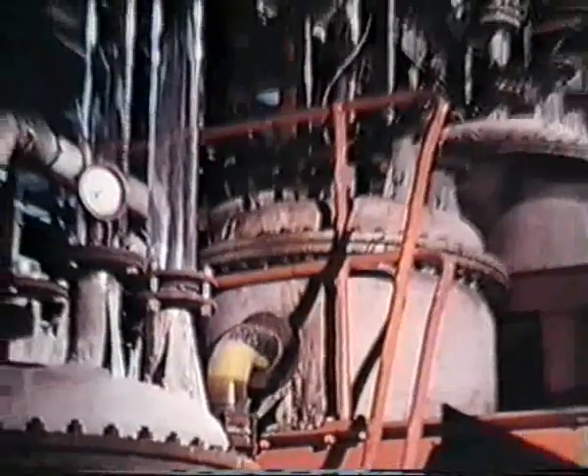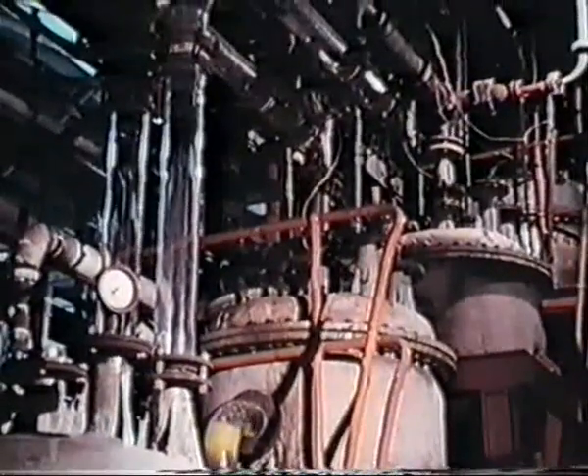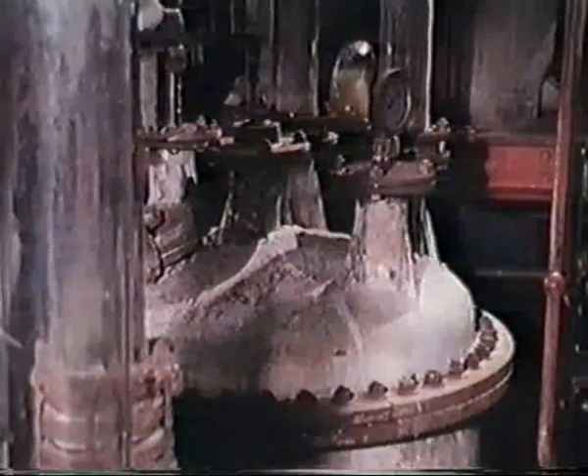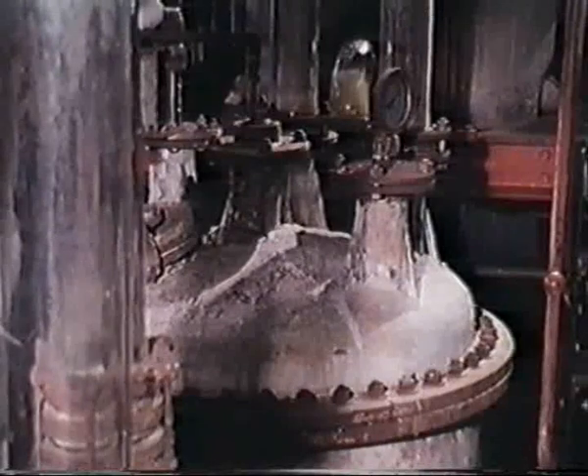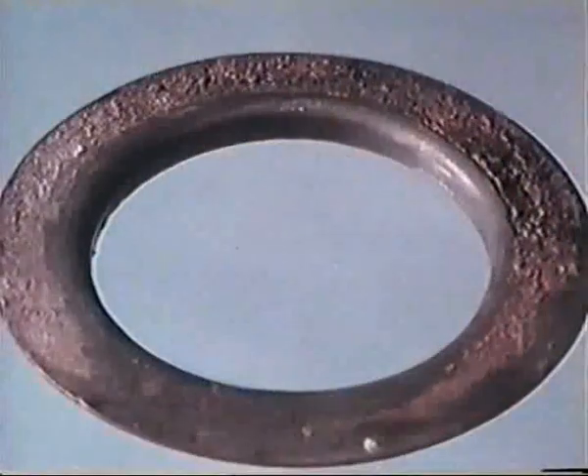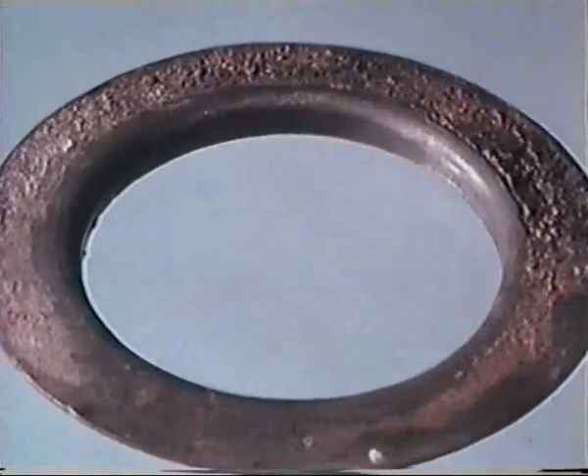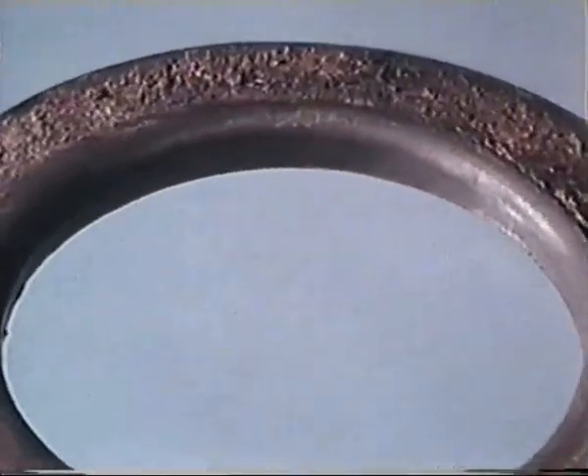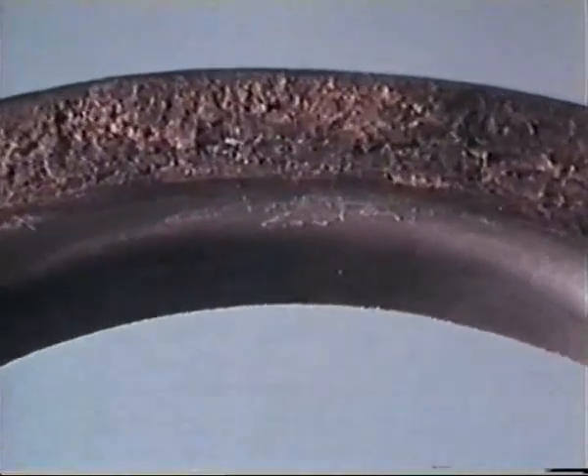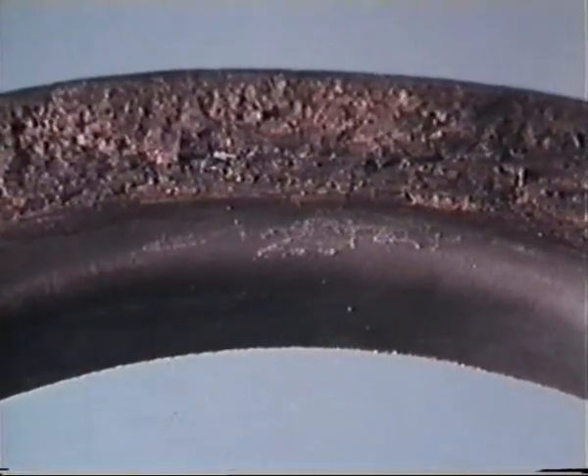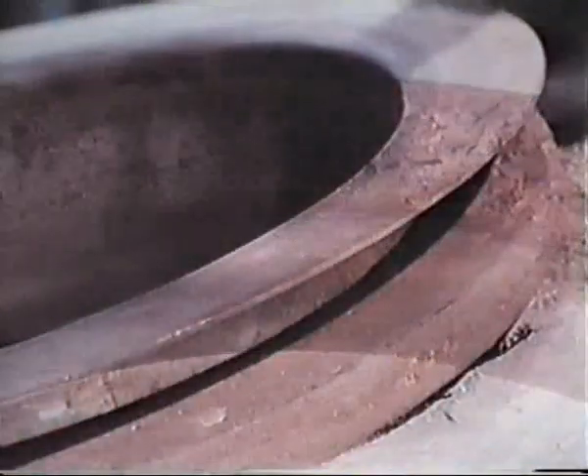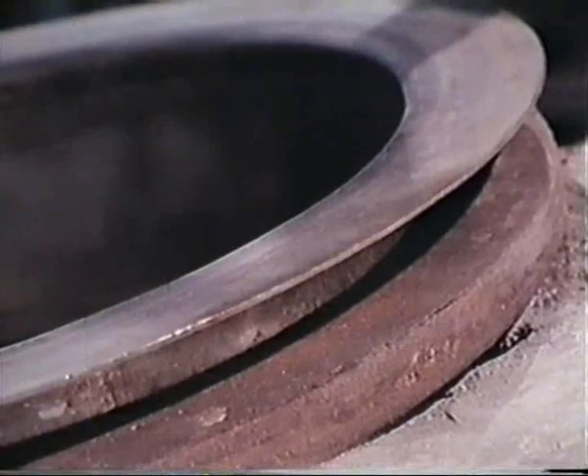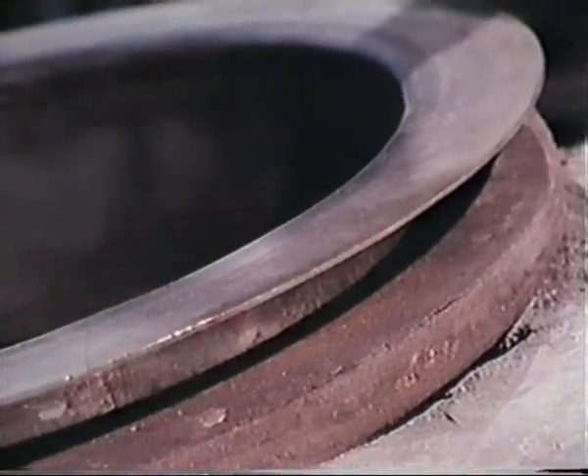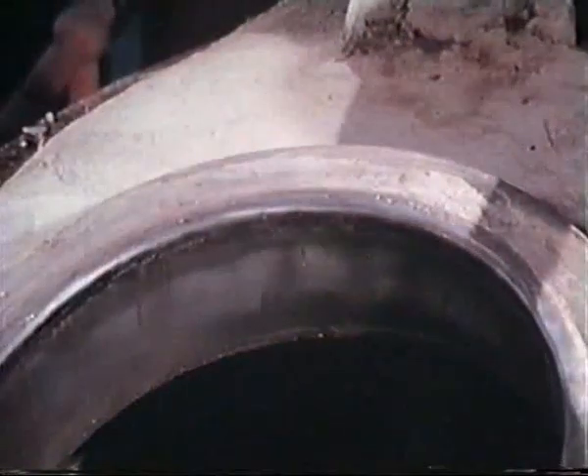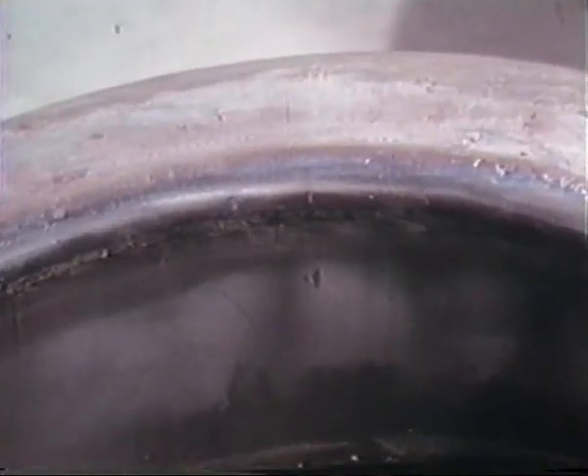In a chemical plant, a more sophisticated example of crevice corrosion occurred in titanium-lined vessels. Titanium is normally highly corrosion resistant, but in this case a crevice was formed at the flange, where severe corrosion then occurred. At breakdown, the cost of the delay in production was considerable. The solution to the problem has been a more precise fit of the flanges to eliminate the crevice. The improved flange shows no corrosion. At the design stage, the cost of the remedy would have been trivial.